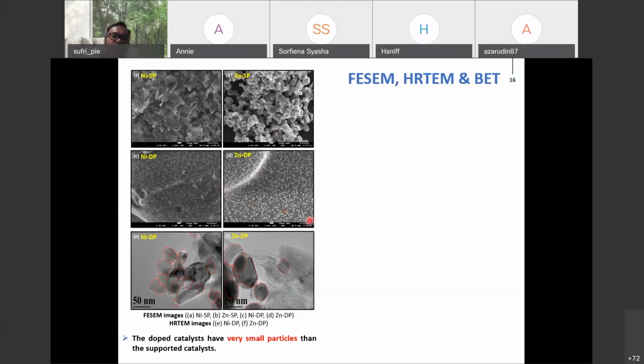So we decided to take the analysis further using high resolution transmission electron microscopy, TEM. By using the HRTEM at a higher voltage, 200 kV, we can observe the small particles clearly. As we can see, the nickel DP and zinc DP appear in spherical form with particle size less than 100 nanometers. Another finding is that the particles of the doped catalyst are also highly dispersed. This is also an important factor to be active in the catalytic reaction.